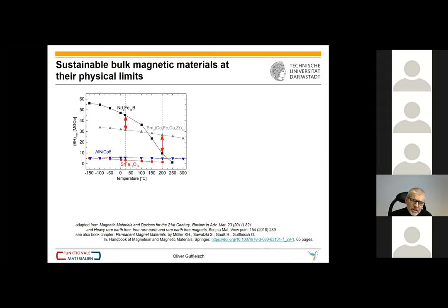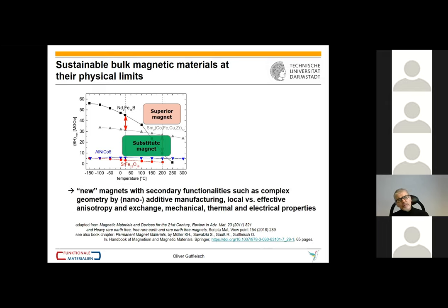So bulk magnetic materials, to bring them to the physical limit. Here I plotted the energy product versus temperature for the most important classes of material. So we have the high performance, high cost rare earths. And you see that 2-14-1 neodymium iron boron is outperformed at already relatively moderate temperatures like 180, 200 degrees by the samarium cobalt pinning type system. And we have here then the low cost, low performance magnets. And we want to basically close this large performance gap by a new substitute magnet and find a superior magnet at high temperature.